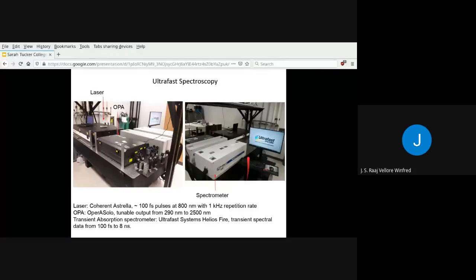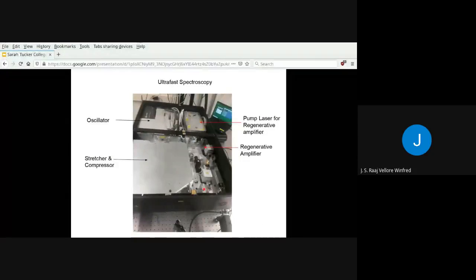In this picture over here, you see a transient absorption spectrometer. This transient absorption spectrometer is capable of studying phenomena that have a lifetime from about 100 femtoseconds up to about 8 nanoseconds. So this setup shows the laser part inside.